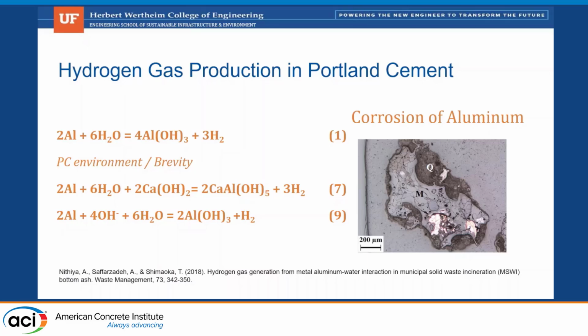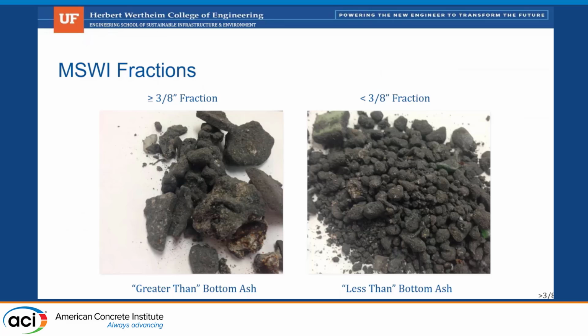aluminum in MSWI. So when we first started looking at MSWI, we started blending, or really segregating it into a coarse fraction, which we call the greater than fraction, and a finer fraction. And so we used a 3/8 sieve and basically said, okay, everything bigger than that we'll keep, we'll use for concrete as a coarse aggregate. Everything less than that we really don't know what to do with. So our first step was, what do we actually do with this stuff?